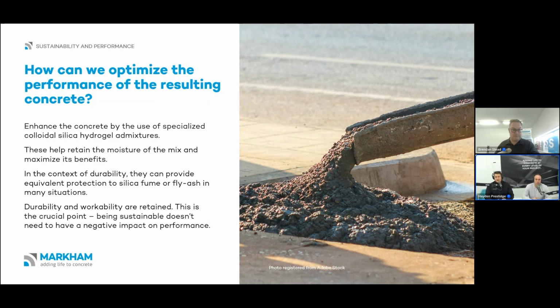Durability is another area. The SCMs themselves, especially slag concretes, have a higher durability anyway. We can take that and further increase it with the use of hydrogels, so you're getting the best in terms of protection there. The only issue, as I've mentioned, is that early strength gain isn't there. So while the end result is great, the logistics and the critical pathways in the construction are affected in terms of getting a construction program on track or keeping it on track.